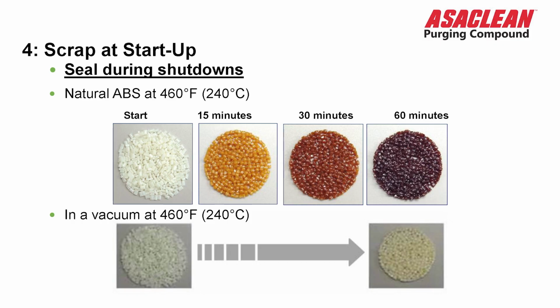If you were to leave an ABS in the system, let's say on a shutdown, and go to cold steel, well, obviously that steel is not going to drop down to ambient temperature immediately. It's going to take a period of time. And within 60 minutes, and we all know that it's going to take longer than 60 minutes for that to go to cold steel, you can see what happened. So getting your production material out of your system effectively as quickly as possible on shutdown before you go to cold steel is extremely important. That's where purge compounds come into play.